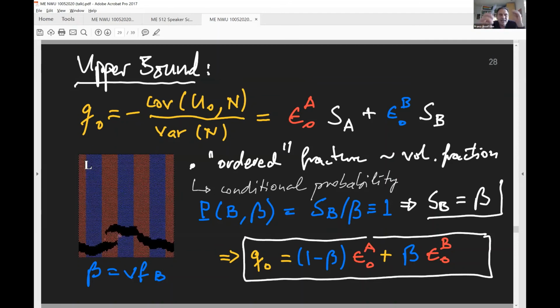So for instance, let's take an upper bound, which is typically the classical layered system here. Please note that I have a volume fraction beta, which is the volume fraction of the blue phase. Now, for such an ordered fracture, one can show by means of conditional probability that this Q0 is simply the linear combination mixture rule of 1 minus beta epsilon 0A plus beta epsilon 0B, which means the fracture energy is just the weighted average, proportional to the volume fraction, mixture rule of this energy. This is the highest, from probability theory, you can show that this is the highest possible fracture energy you can obtain given the likelihood of fracture occurring in phase A or phase B.